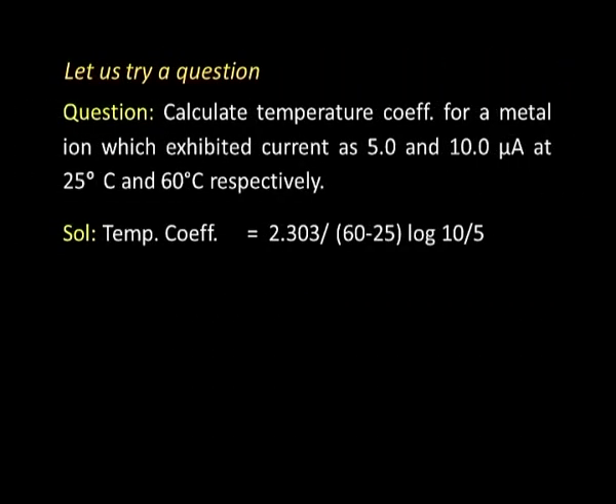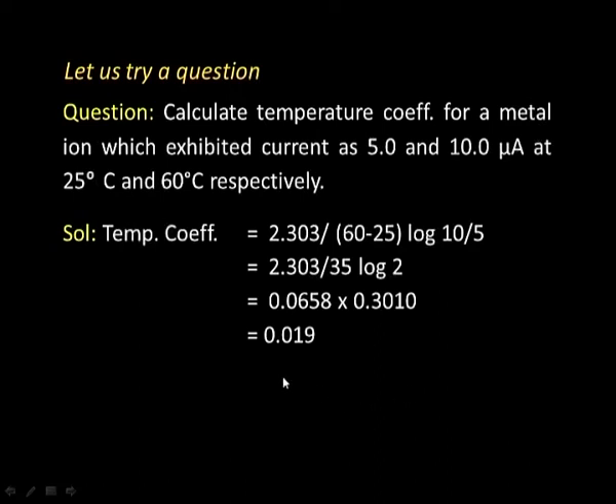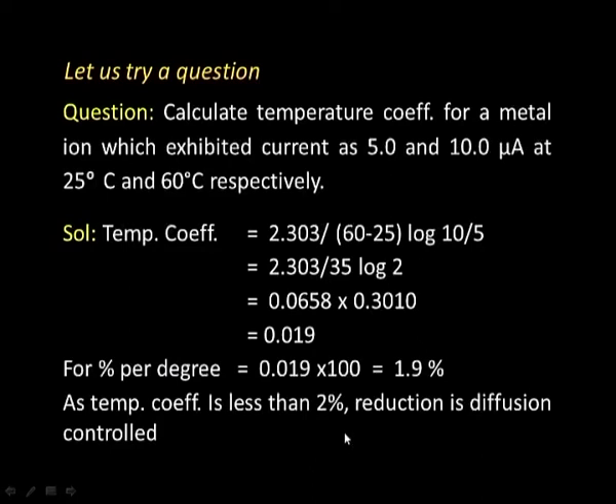Let us try a question. Calculate temperature coefficient for a metal ion which exhibited current as 5 and 10 microampere at 25 and 60 degrees respectively. The solution is, we know temperature coefficient is equal to 2.303 by 60 minus 25, the temperature difference, log 10 by 5. This comes as 2.303 by 35 multiplied by log 2 and the result is 0.019, and if we change it to percentage per degree, this comes out as 1.9%. As temperature coefficient is less than 2%, we can conclude that reduction is diffusion controlled.